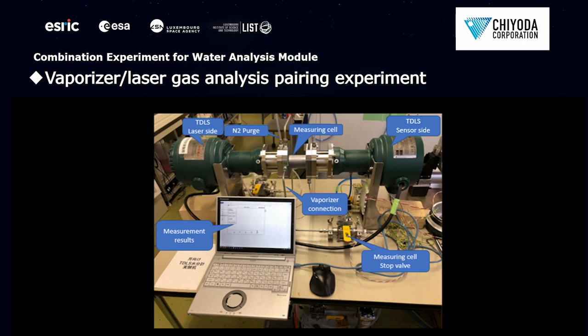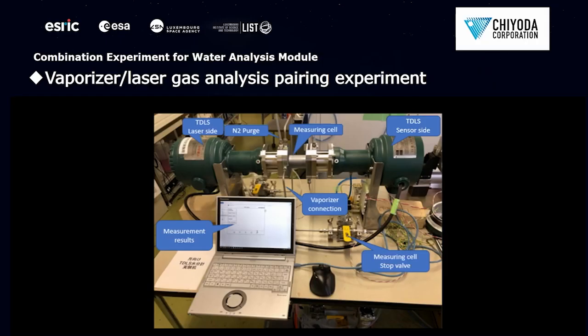And this is the experiment we have done. We put the TDLS and connected it to the vaporizer, which is developed by Chiyoda Corporation. And we connected this entire system to a vacuum pump so that we can simulate the vacuum condition on the lunar surface. And we injected a small amount of water into the vaporizer by using a syringe and heated it up to 100 degrees Celsius.